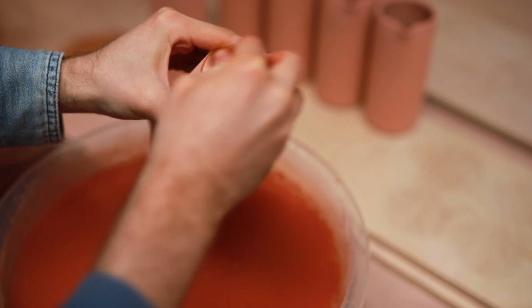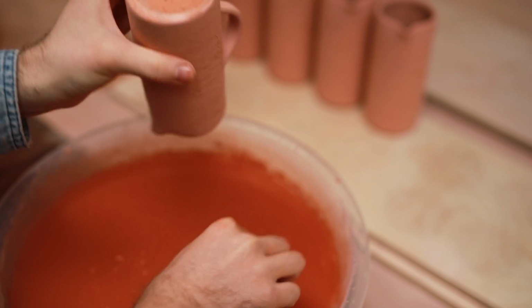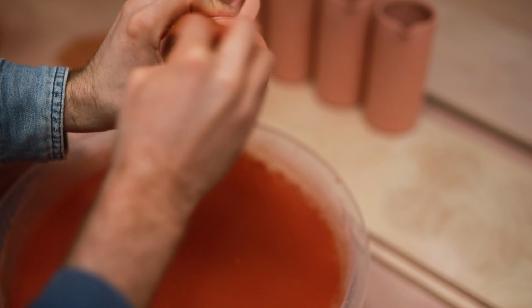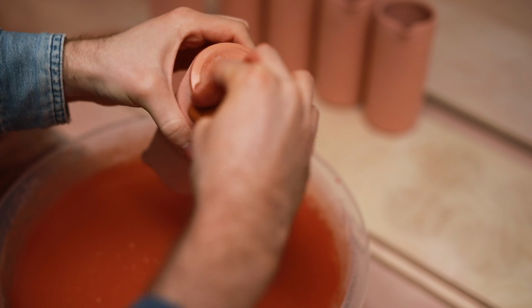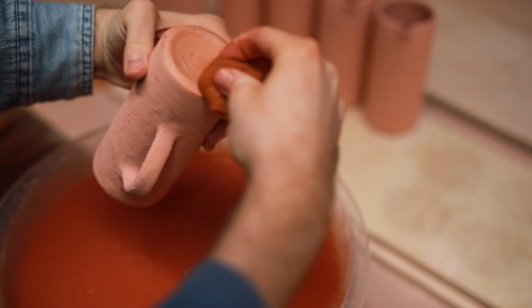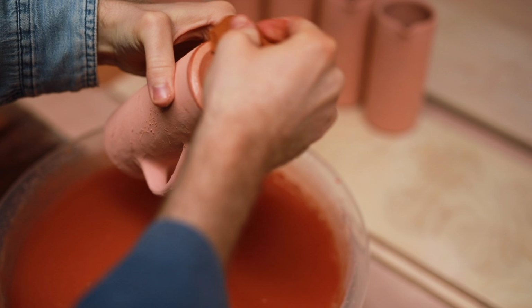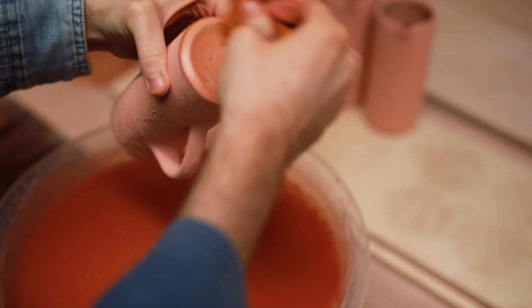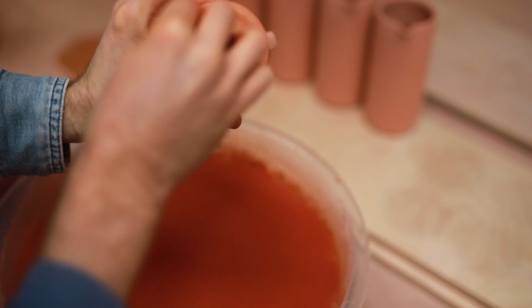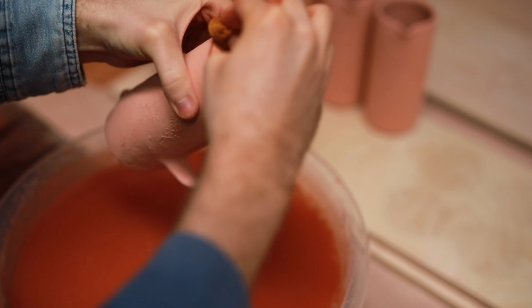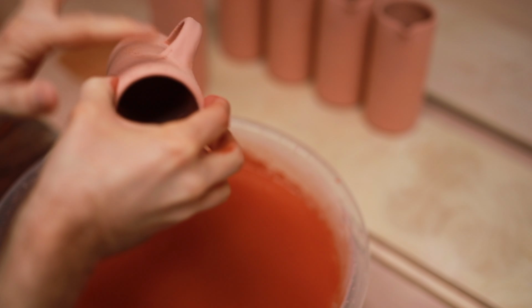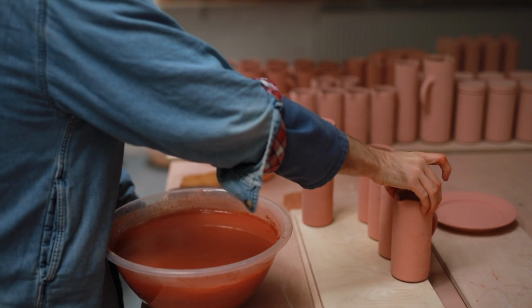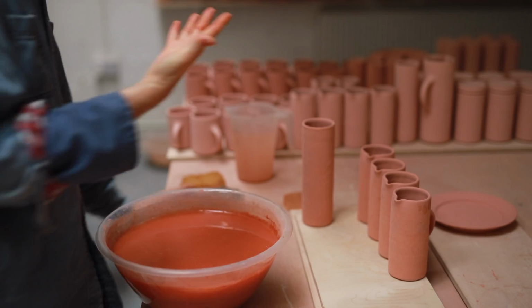Even though it's waxed, small particles of glaze will settle onto it. So I use a wet sponge to go over it, removing the excess glaze and also neatening up the line where glaze and clay meet. I catch all this wasted glaze in the bowl of water beneath, and eventually I can add this back to my main bucket of glaze later on. So there's very little waste. And now, that's it. I'm ready to pack the kiln. After, of course, I've glazed and done the same process to around 200 more pieces.